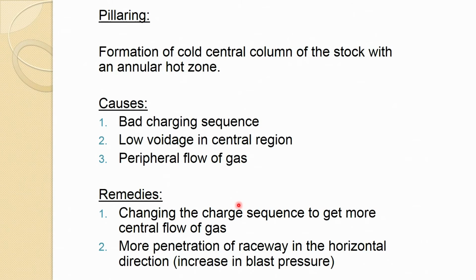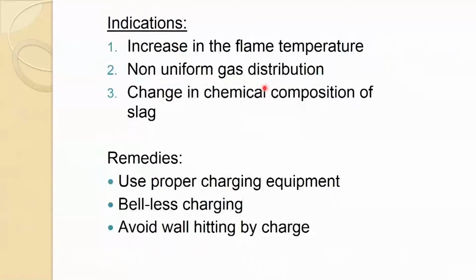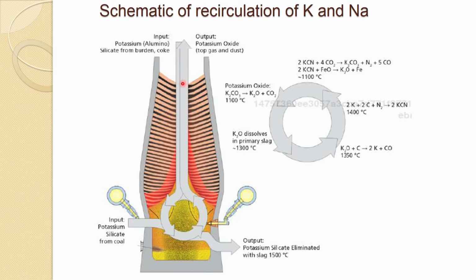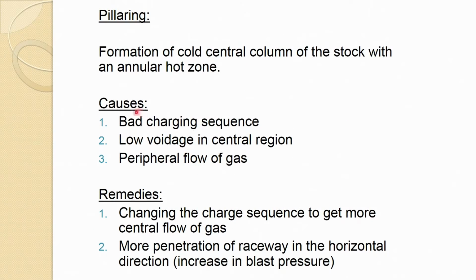Another abnormality or irregularity is pillaring. It is the formation of a cold central column of the stock with an annular hot zone. If we go back to here, this is mostly if this center region has less voidage in the charging, then the reduction and heat transfer would be low here, and this will form like a pillar here, and that is what we are talking about. It is caused by a bad charging sequence, low voidage in the central region, peripheral flow of the gases.